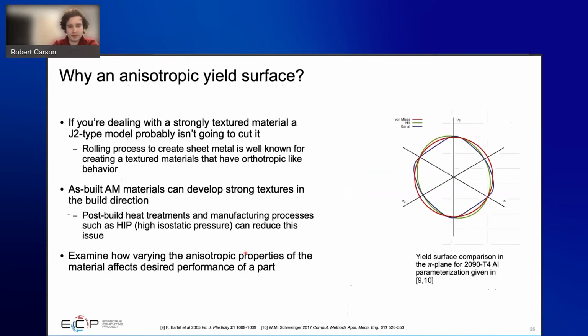But as I mentioned earlier, we don't really want to use a J2 type model. The reason, as we saw earlier, is this strongly textured effect in our material, and J2 models just don't do well with that because they assume everything's isotropic. When you're looking at macroscopic type models, there are a lot of different ones out there. This is because within manufacturing, people wanted to model things such as rolling processes for sheet metals, which they know have a very textured, orthotropic-like response.